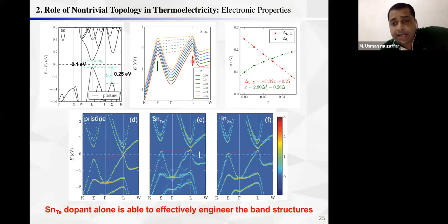So after introducing the anti-site defects in this system, we find that with the doping, 1%, 2%, 3%, or 5%, you can see that the slope of this band, this is the L point light hole band, and this is the heavy hole band, decreases. It means that they are merging, they are coming closer to each other. More simplistically, you can see that with the increase of the anti-site doping, the energy difference between these two bands decreases significantly. And this green band represents the fundamental band at the L point. With the increase of the anti-site doping, it is significantly enhanced. So these two parameters are good for the Seebeck coefficient, as I mentioned previously.